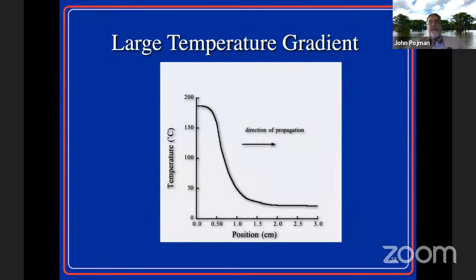And these are centimeter marks. So this is just propagating. We started it. And once you start it, it'll go no matter how long the sample is. And here it's now starting another reaction. So that's very easy. These experiments are extremely easy to perform with some systems. They're characterized by having a large temperature gradient. It can get up to over 200 degrees centigrade.